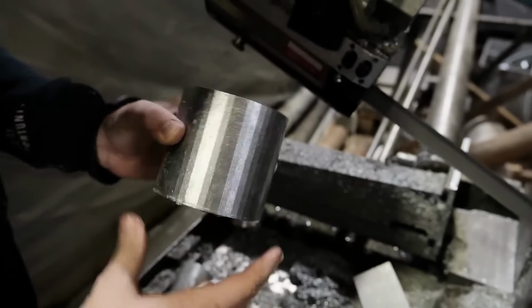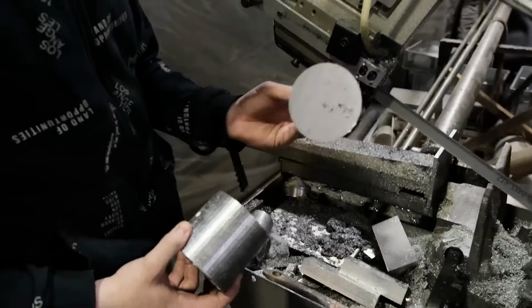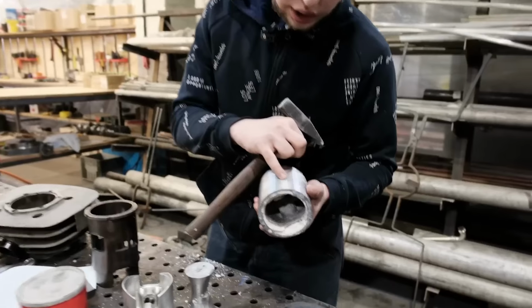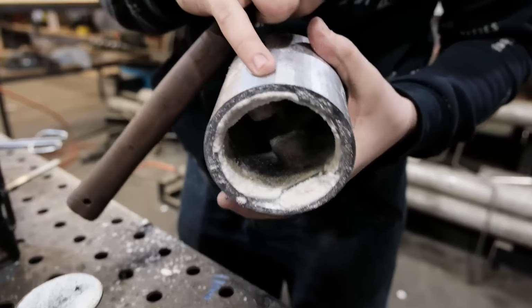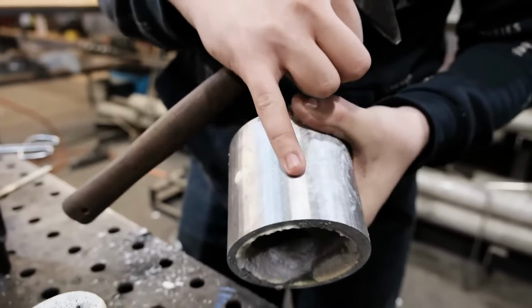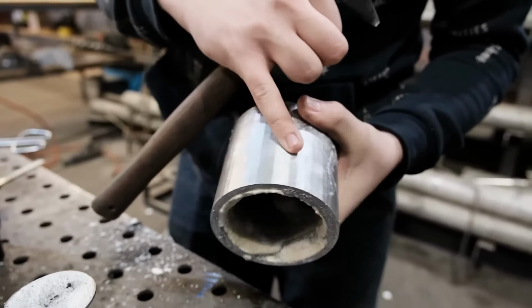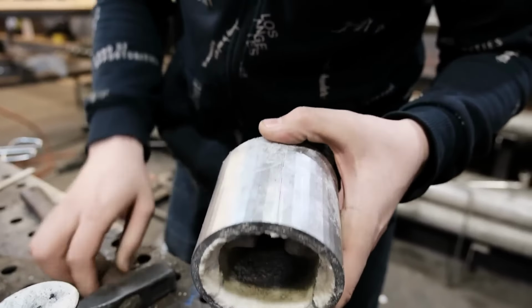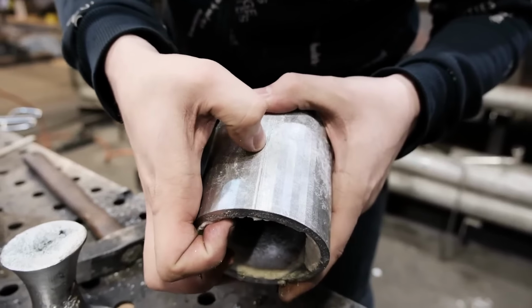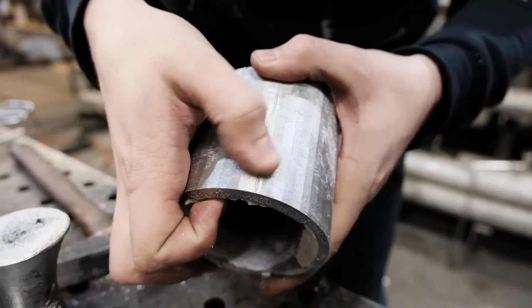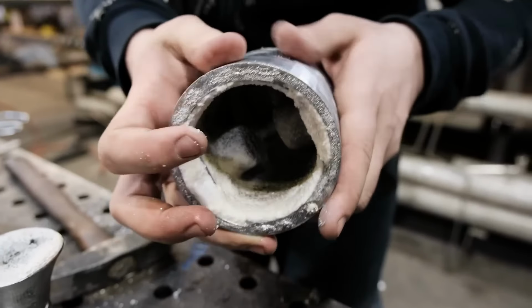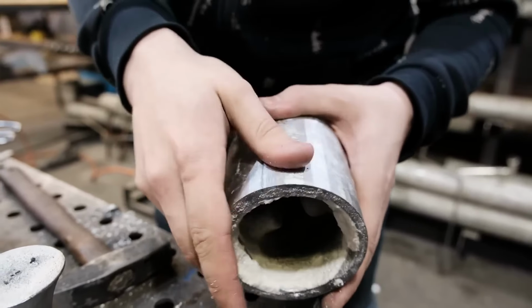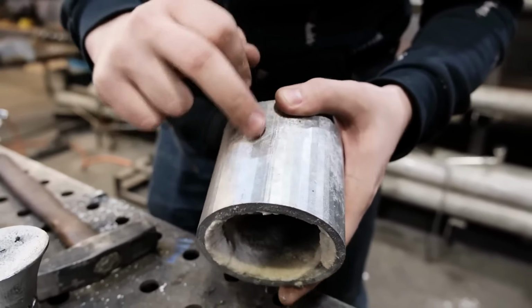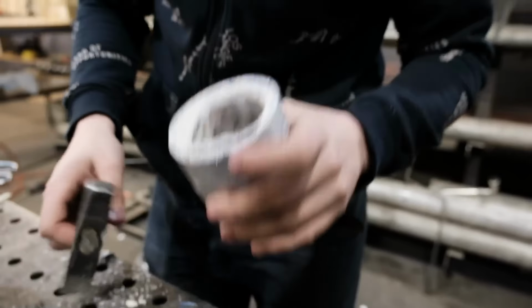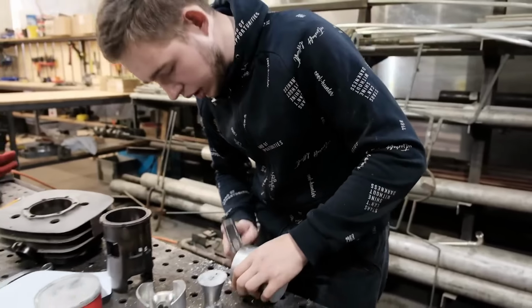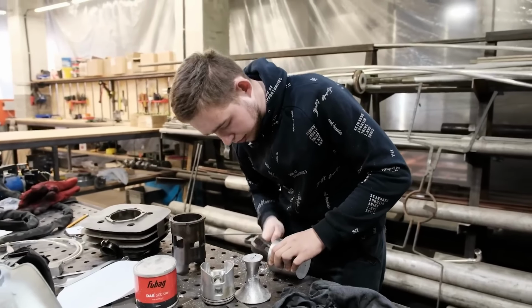As for the casting quality itself, it is actually quite remarkable. You can even see the individual layers that result from the 3D printing process. You can also clearly see the faceting created by the 3D printer itself. Here, you can even see the seam from the 3D printer where the joint was made. So this method perfectly reproduces the geometry, the ribbed layers, the seam, and also the inner surface, capturing all of these details with impressive accuracy.